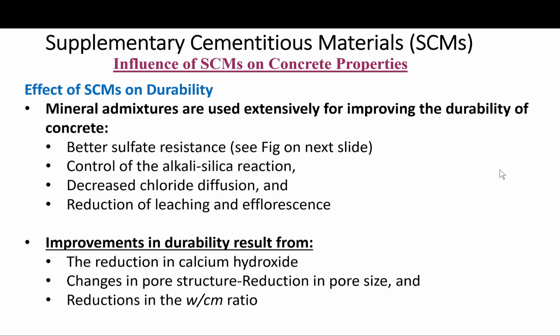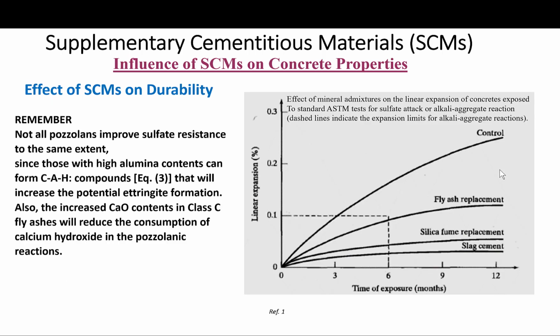It is also known that not all pozzolans improve sulfate resistance to the same extent, since those with high alumina content can form calcium aluminate hydrate compounds, as shown in equation 3 before. These compounds increase the potential for ettringite formation. Also, the increased calcium oxide content in Class C fly ash will reduce the consumption of calcium hydroxide in the pozzolanic reaction, so the benefits from fast removal of calcium hydroxide will be less effective for Class C fly ash.